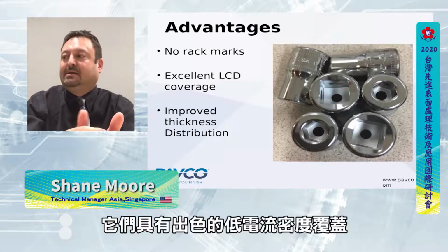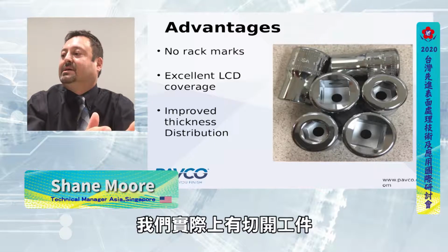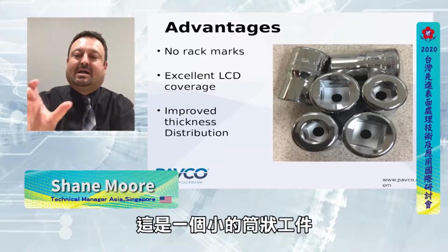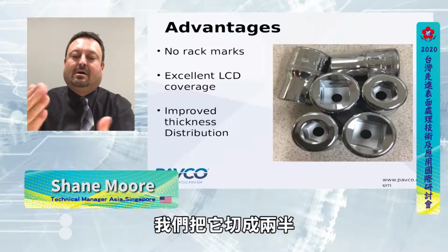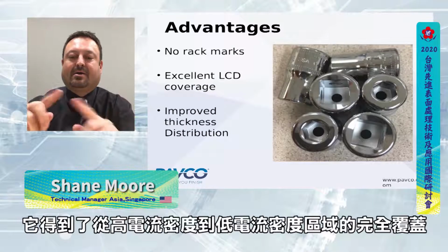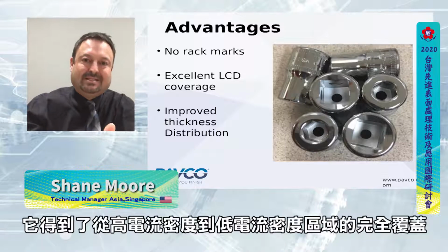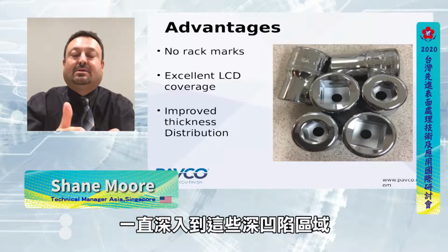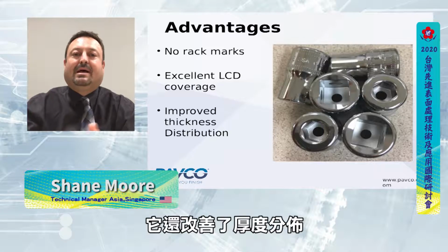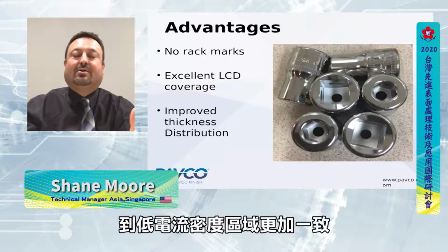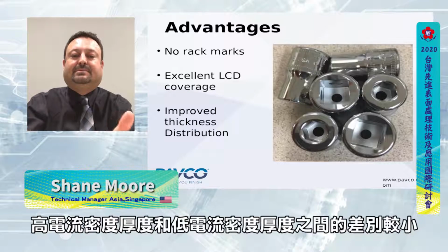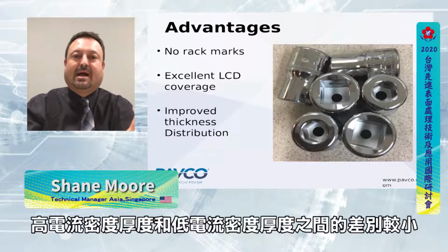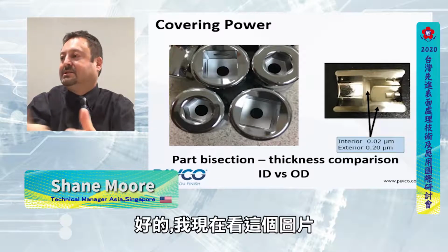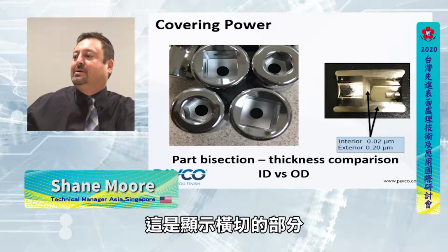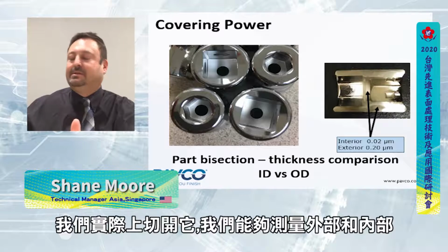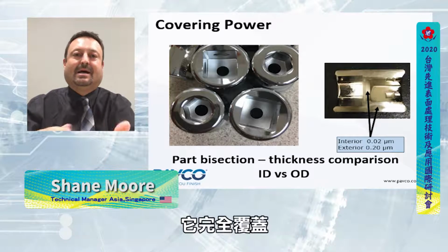Okay, some of the other advantages: no more rack marks. There's no rack marks at all. It has excellent low current density coverage. We actually cut a part open and we were able to measure it. It was a socket, just a small socket. We cut it in half and it got complete coverage from the high current density to the low current density area, all the way down into these deep recessed areas. It also has a very improved thickness distribution because the current applied is so much more consistent from the high current density area to the low current density area. It's a lot tighter. It's a smaller difference between the high current density thickness and the low current density thickness. Actually, I'm looking at slides here. This is showing a part bisection where we actually cut it open, and we were able to measure the outside and the inside, and it was completely covered.